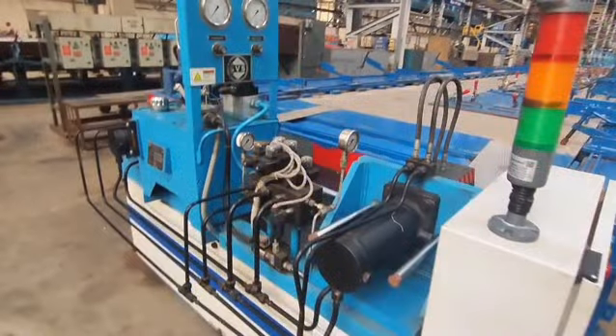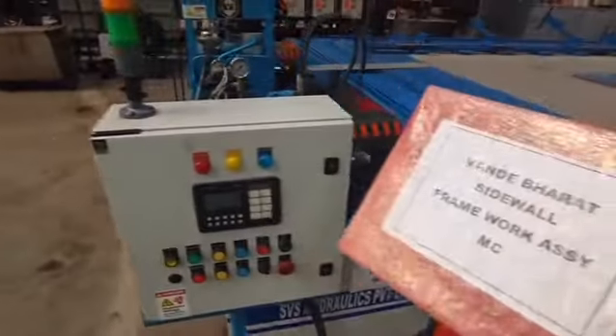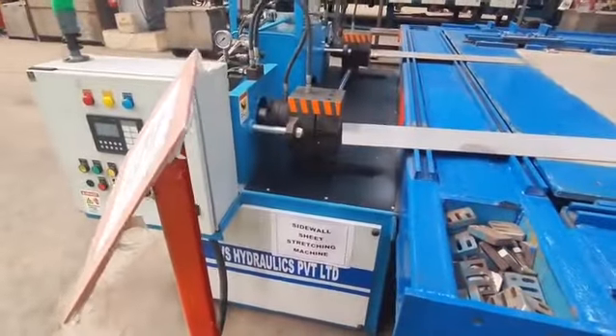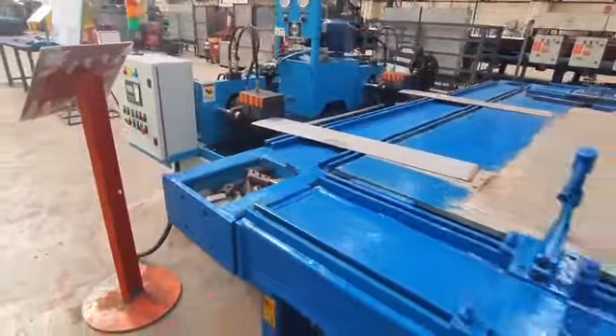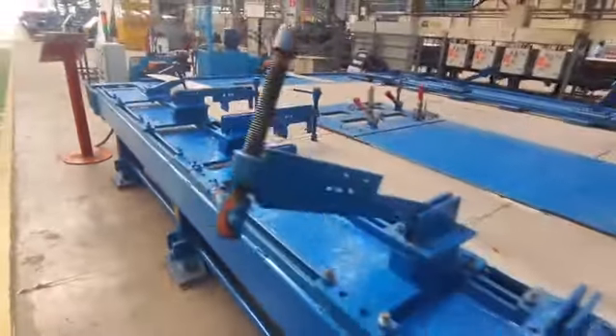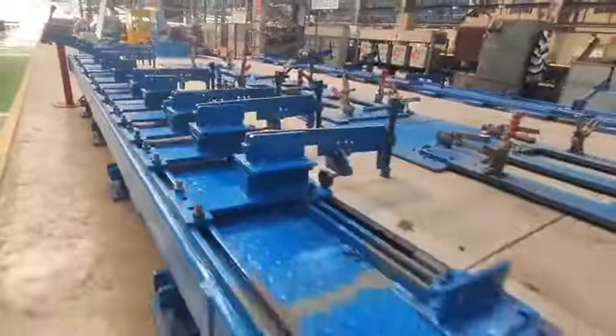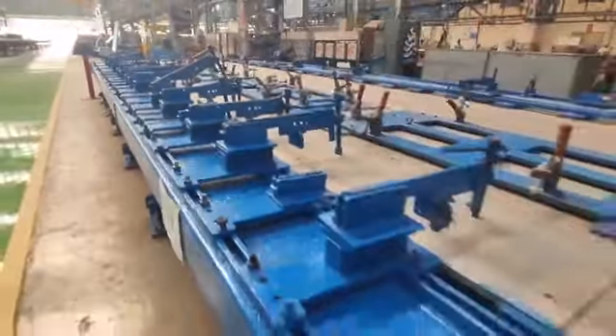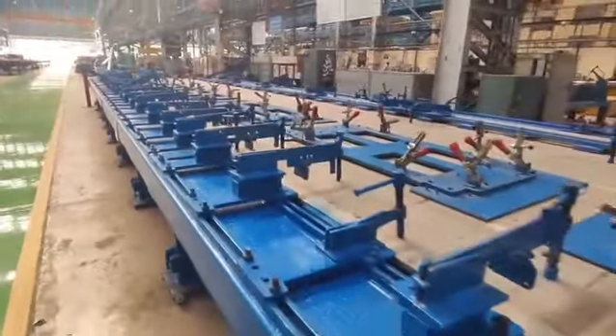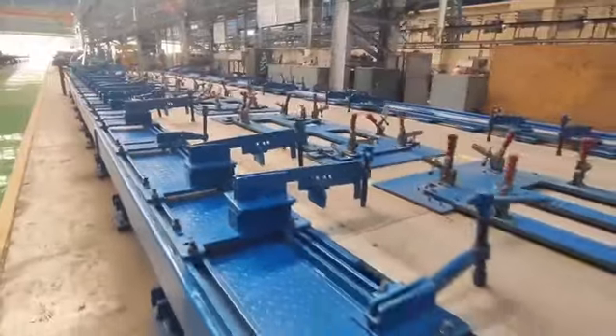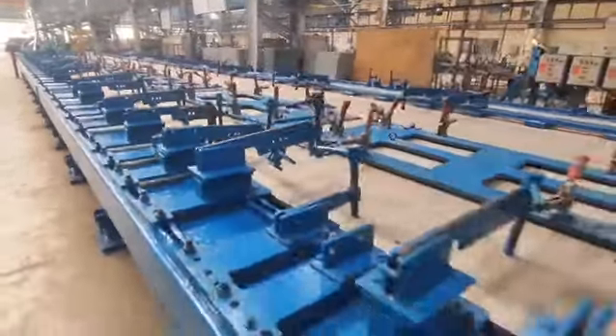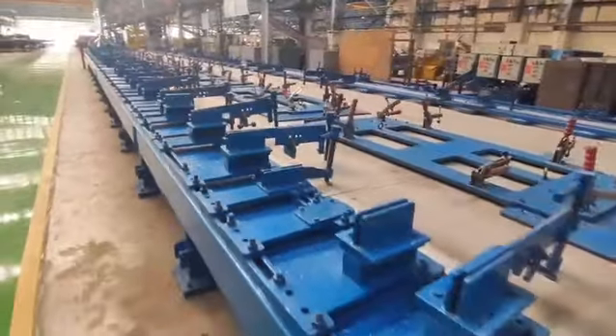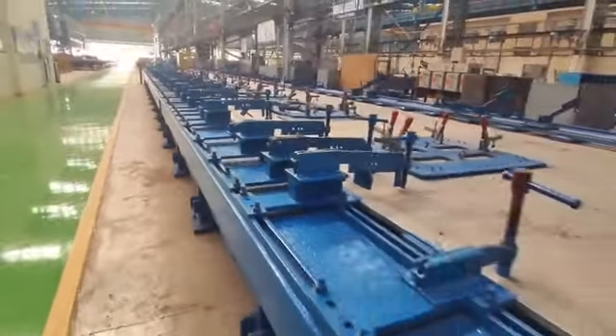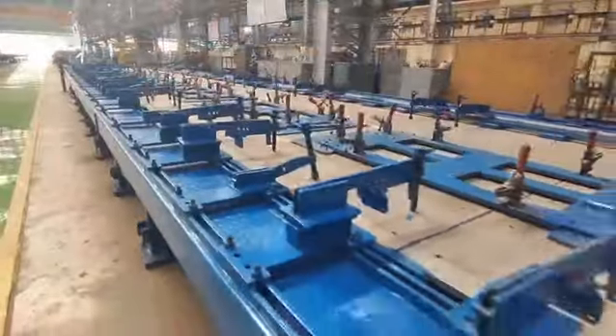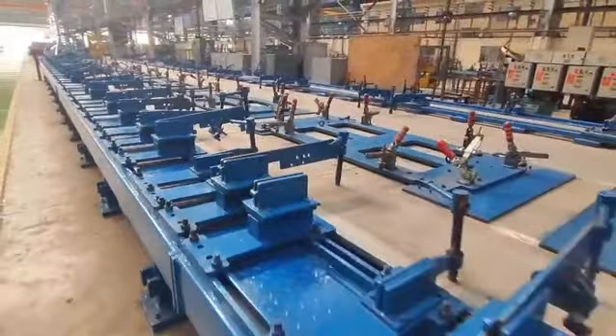This is a sidewall stretching machine. After placing the sidewall sheet on the table, all clamps are tightened properly and both ends are welded. One end is welded to the hydraulic stretching machine, whereas the other end is welded to the table itself. The stretching machine stretches it with 120 kN force. In this uniformly tensed condition, the framework assembly, that is horizontal and vertical members, are tack welded to the sidewall sheet. Stretching is done to compensate for the distortion due to uneven heat input into the sidewall assembly during welding. After tack welding, full welding of the frame structure is also carried out in this stage after ensuring the dimensions. For full welding, a center to outside sequence is followed as per WPS to avoid distortion.